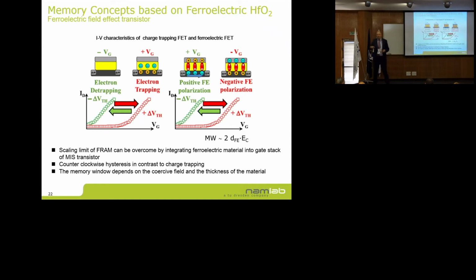I have met a few people here already that have worked with me previously on charge trapping devices, and we all know if we put a charge trapping layer into a transistor, we can use it as a non-volatile memory. And typically, if we apply a positive voltage, we get a positive VT shift, and the other way around if we apply a negative voltage. If we use the ferroelectric instead of a charge trapping layer, it will behave exactly the other way around. Positive voltage will end up in a negative VT shift.